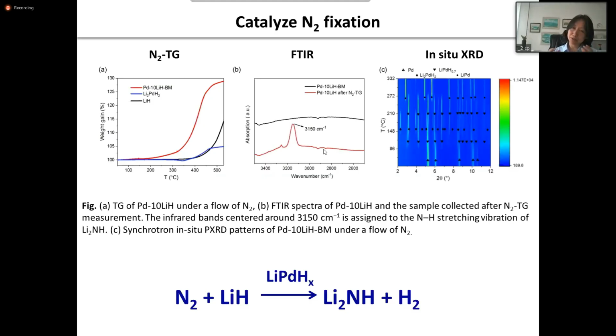We notice that when we put palladium into lithium hydride and mix, we can efficiently fix dinitrogen into our material. You can see from the red curve here, the nitrogen TG, the weight gain starts earlier, at lower temperature than the other samples, which shows that the lithium palladium hydride probably catalyzes the nitrogen fixation reaction. And we did observe that after nitridation, we have the nitrogen-hydrogen bond stretch here. Combined with in situ X-ray diffraction, we know that lithium palladium hydride is very highly likely to behave as a catalyst for dinitrogen fixation.